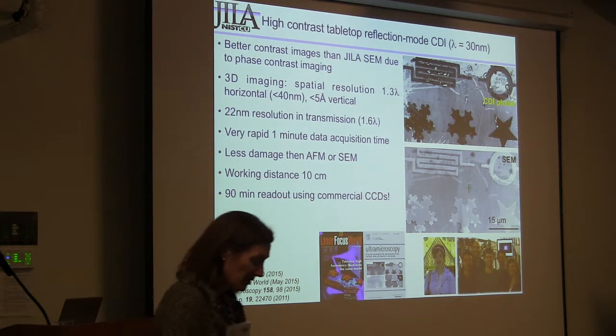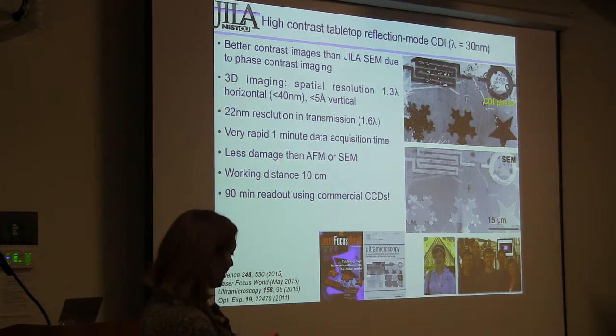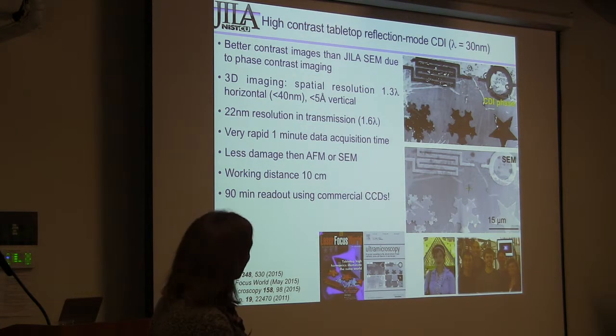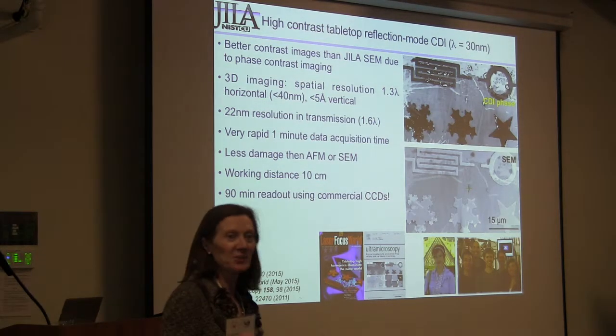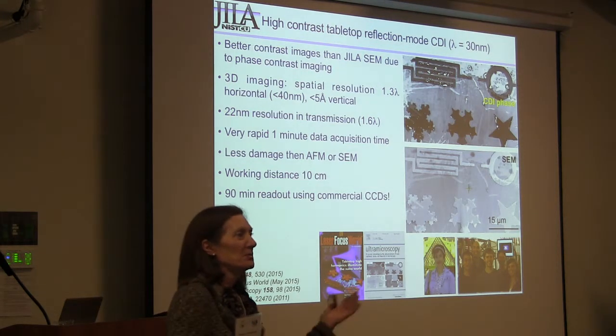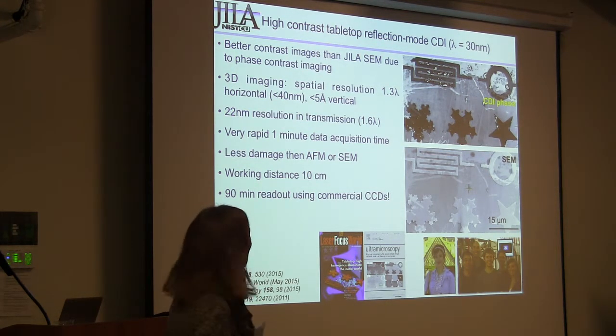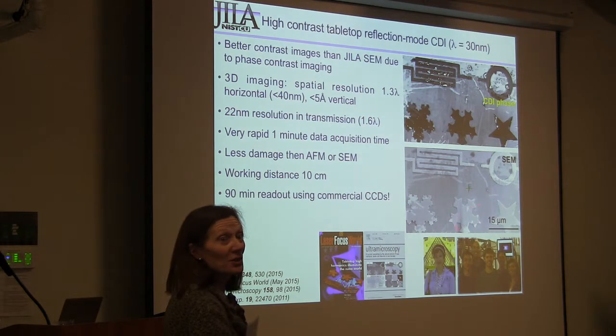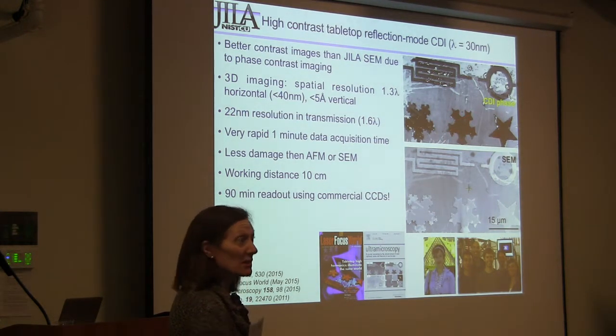So our students took a silicon wafer and made nanostructures of titanium on the silicon wafer, and this is the scanning electron microscope image using the JILA scanning electron microscope, and this is our high harmonic phase image. And if you look here at the silicon wafer, of course, we're not doing this in a clean room, we just want to learn imaging, so we don't care if crud gets on our sample or if we scratch it. But the thing that was exciting to us is that you can't see the scratches using this kind of electron microscope, but you can see them better with the harmonic illumination.